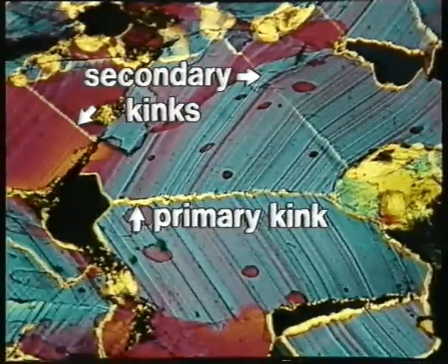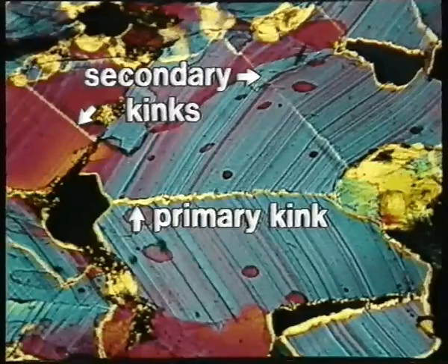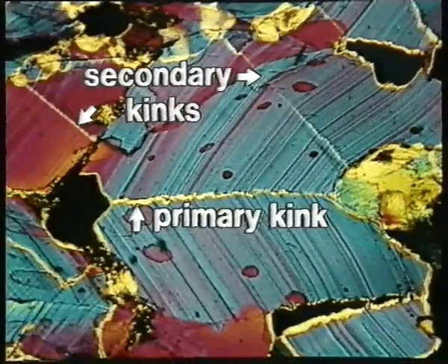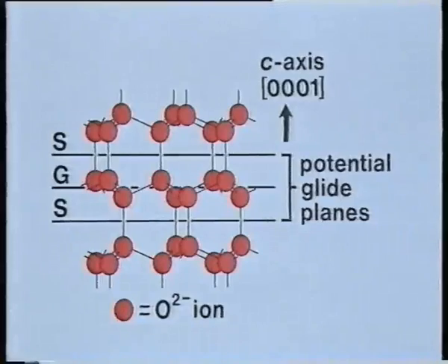Polycrystalline ice will be used in the following set of experiments. These experiments represent two-dimensional models of a material with one slip system. Ice is hexagonal, and in common with many hexagonal and pseudo-hexagonal minerals, undergoes translation glide on crystallographically controlled planes.